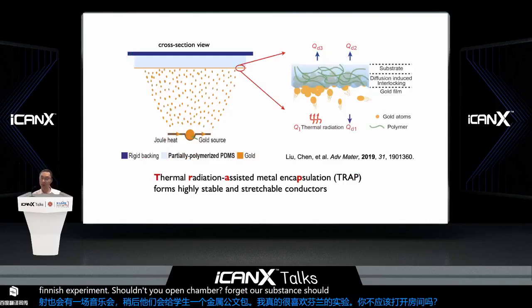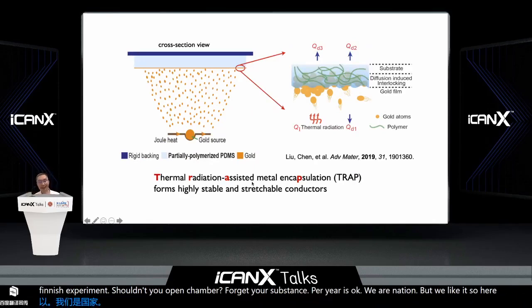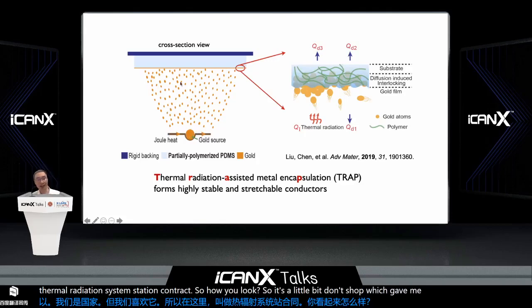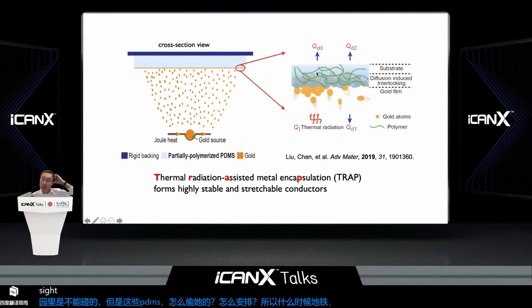So that's why, inspired from here, a new design came out. It's okay, we still have thermal radiation, but we like it. Here we call it thermal radiation assisted metal encapsulation, called TRAP. So how does it work? This is the metal, a gold source. We use heat to go from solid state to gas state, and then it deposits on the PDMS. But this PDMS is half-cured, still with some monomer. So when the metal reaches the surface, it diffuses inside, and the thermal radiation further polymerizes the PDMS, which surrounds the encapsulated metals embedded in the substrate.